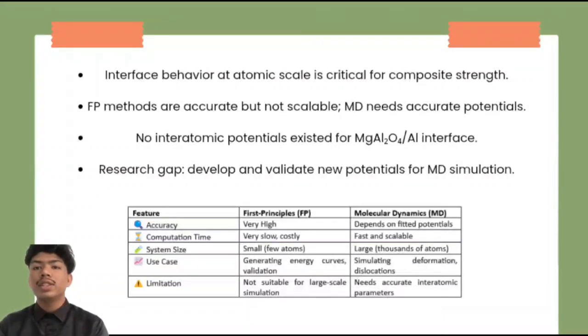At the time of this research, there were no validated interatomic potential models for the magnesium aluminate-aluminium interface. This made it impossible to perform reliable atomic scale simulation of how the interface behaves under mechanical stress. Therefore, the problem this study addresses is the lack of accurate, practical, and validated interatomic potential parameters for the magnesium aluminate-aluminium interface. Filling this gap is essential for enabling large-scale simulations and for revealing the true nature of the strengthening mechanism at the interface.